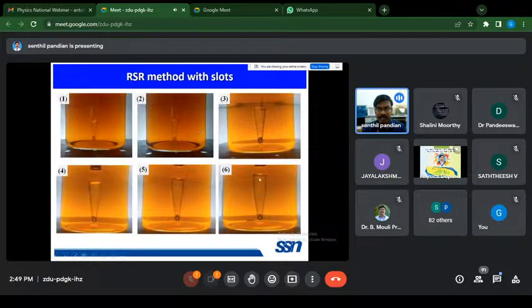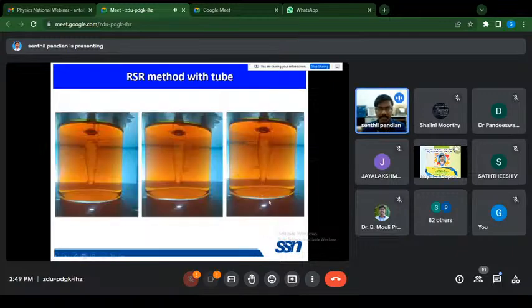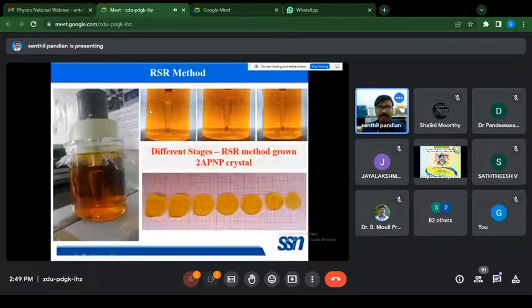You see the transparent 4-dimethylamino derivative single crystal. Here one is able to avoid the impurity segregation. One can minimize the impurity segregation in this RSR method compared to the SR method grown crystal. This is the RSR method with the tube, this is the RSR method as-grown crystal, and this is the cut and polished wafer.